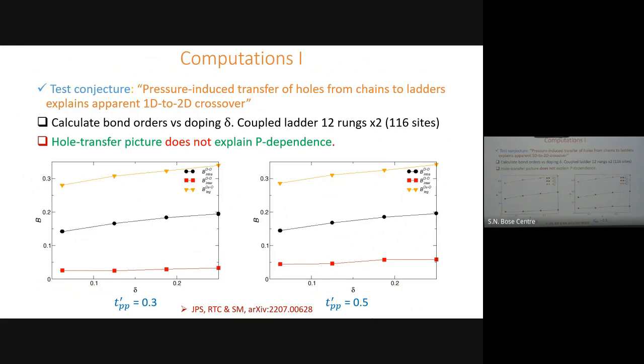The interladder oxygen hopping is flat with respect to doping. Why are we plotting it as doping? Some of the experimentalists said that maybe when I bring the layers closer together, and that is related to your question, Dr. Manohar, there is transfer of holes from the chains to the ladders. So that's delta. And as a result, the dimensionality increases. So we plot from 0.0625 to 0.25, and it is flat. This is the interladder. The dimensionality does not change.